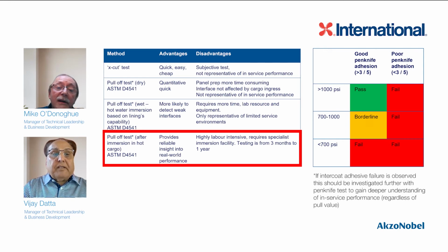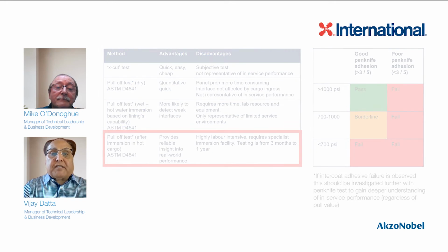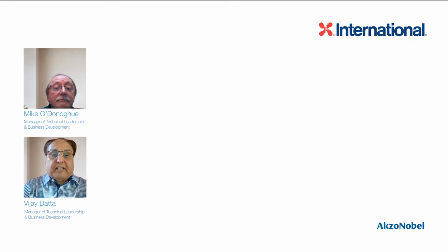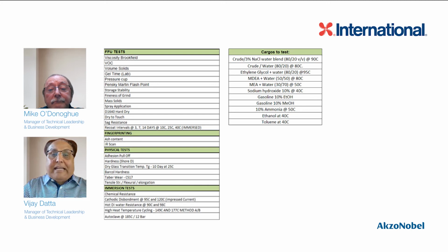Now we also ran a wide range of tests on Enviroline 376, and one of the key tests here is a 12-month immersion test into various cargoes. So when the coating is put into the marketplace for a purpose, we make sure what is going to be carried into those tanks, and we do test those cargoes, as you can see here: crude oil with water, ethanol, various amines, sodium hydroxides, gasoline and gasoline blends for up to 12 months.